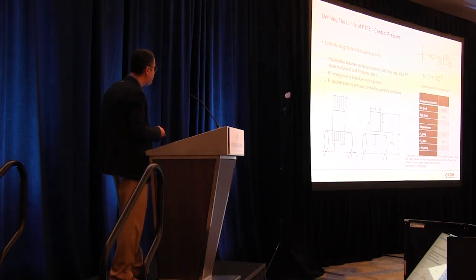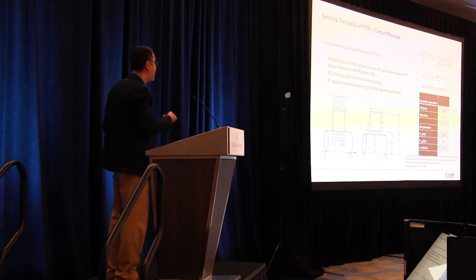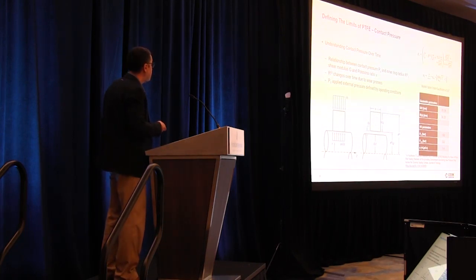And we are trying to determine or estimate that contact pressure under the effect of this effective gas pressure. This gas pressure is given by a function of the inlet pressure of the gas and also the discharge pressure of the gas. For our case here, we are using hydrogen, and the effect of the gas is included in the specific heat numbers here, which come from the hydrogen itself. For this example, we are using a discharge pressure of 350 bar and inlet pressure of 150 bar. This gives us an effective pressure we will use as our loading pressure on the ring. One other thing I need to make a note of is that some of the geometrical parameters like the radius or the height of the sample are time dependent in this process, because as you wear out the sample, the radius will change, so that's also taken into account in this model.